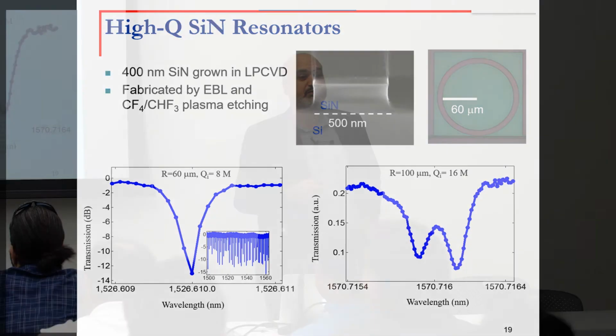The problem with silicon nitride is that it cannot be tuned. There is no reliable, efficient tuning mechanism to change its index of refraction. So now we have a material that is ultra low loss, perfect for a lot of applications. We have a material that is tunable, silicon, that is not ultra low loss. And of course, the natural way of thinking is to somehow combine the two, if we can, to just marry the advantages of the two.